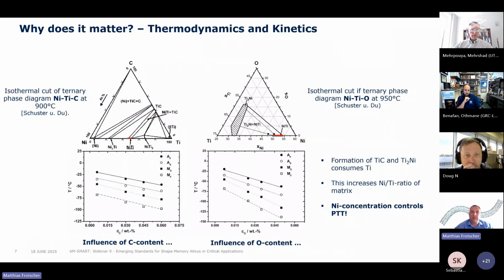Looking at the ternary phase diagrams of nickel-titanium-carbon and nickel-titanium-oxygen, it becomes obvious that Nitinol can solve a significant amount of carbon, but is forming TiC in the matrix upon solidification. And the diagram on the right shows the same for Ti2Ni being able to solve oxygen. That's why it is so important to control both, so that the formation of inclusions is reduced to a minimum, ideally. You can also see that both increasing carbon and oxygen content shift the phase transformation temperature downwards. The reason is that titanium is consumed during the formation of these secondary phases, and thus the nickel content in the matrix increases. So it is not just about fatigue, but also about achieving your desired phase transformations for the application you have in mind.